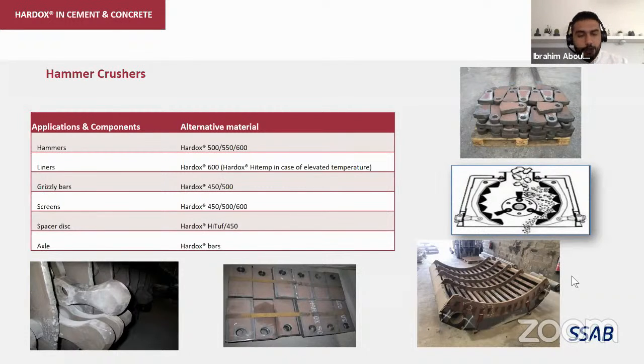We have a very nice solution that has proven a lot of success cases worldwide, which is using thinner hammers and larger numbers. So if you have 10 hammers, each one is 120, you use 20 hammers, each one is 60 millimeter in thickness. Or you can use sandwich hammers or twin hammers welded with electrical pockets, for example. And using 500 and 600 has proven a lot of success in this application, especially worldwide.